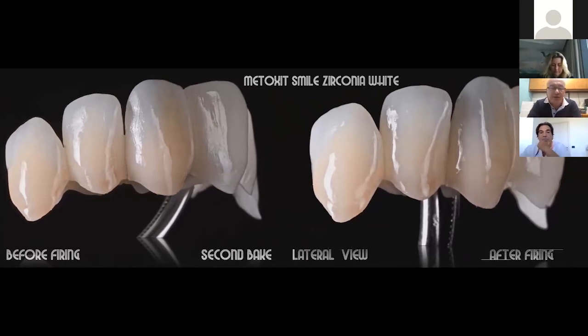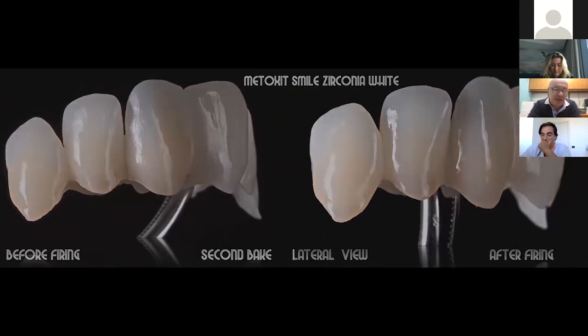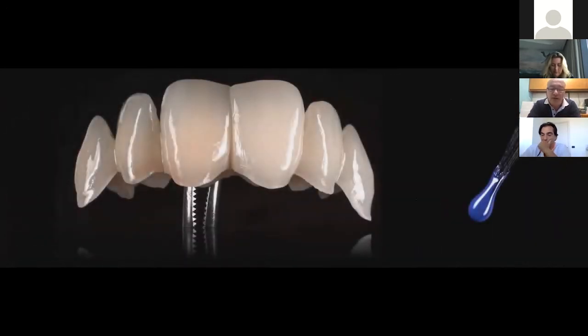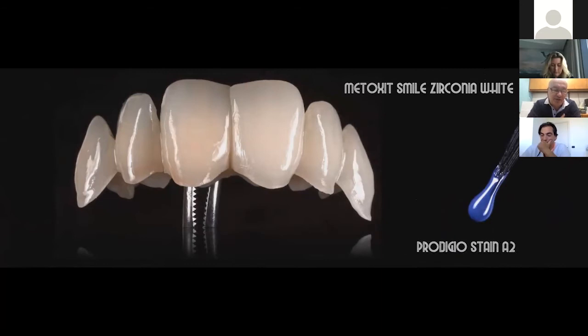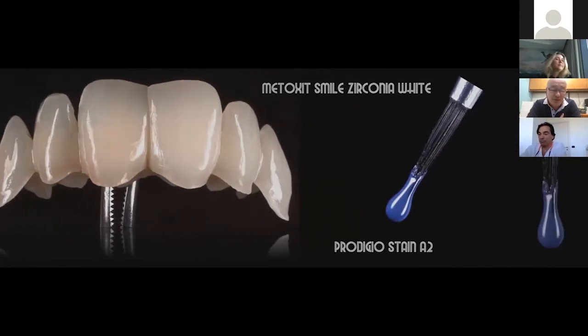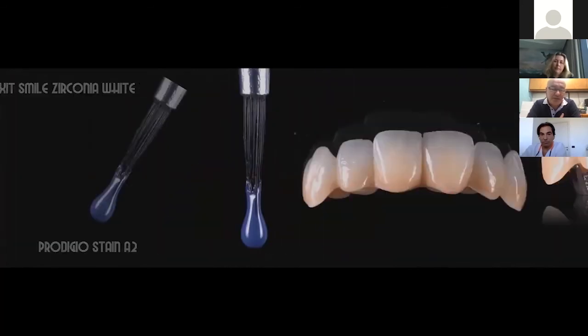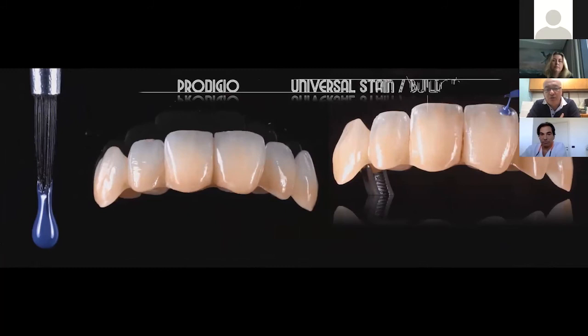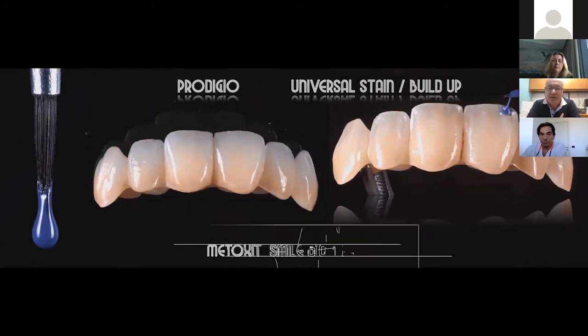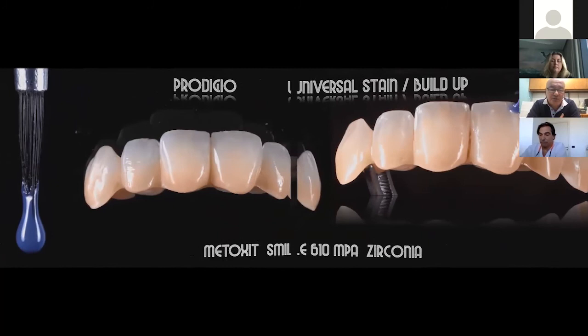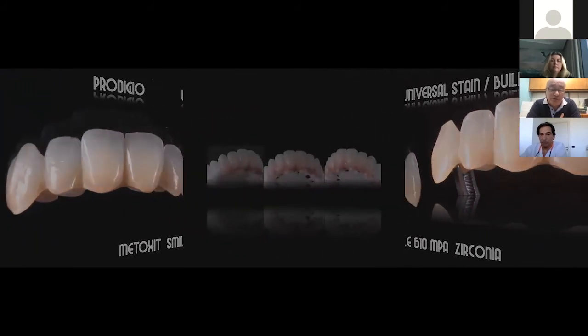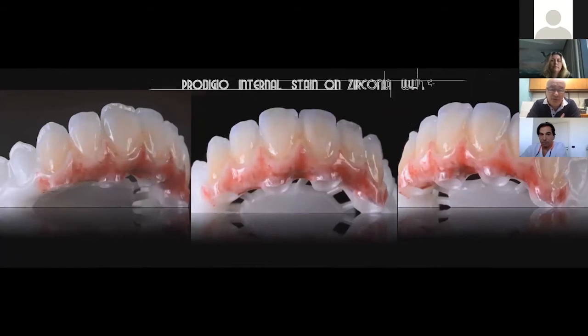In a different view, you can really see the three-dimensional effect of those stains. This is a very simple way to turn from a white zirconia to any color you want. Some technicians prefer not to use the A1 or A2 color. They prefer to start from white, like Michele was showing about the pre-sintering color, and after the sintering you can use those stains. As you see on the right, it's just a minimum cutback, and you can really build with this ceramic stain. They are in paste, this Prodigio, and you can build the shape. You can also include the pink area, not only making teeth.